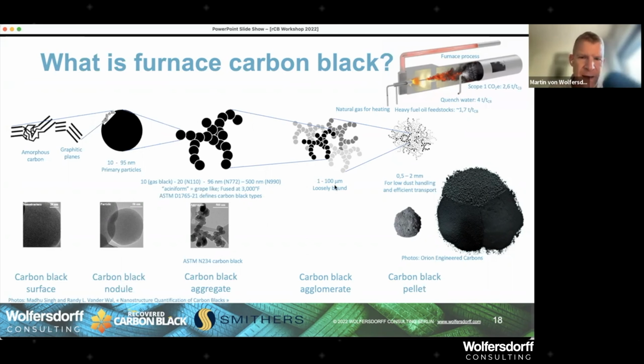For the recovered carbon black, the aggregate is not fused, but it is the compound of carbon blacks, of the ash, and of the volatile hydrocarbon and the solid hydrocarbon. So the particle size in the case of recovered carbon black is for the aggregates, not the agglomerates, Ignacio. So, and then we have the pellets.